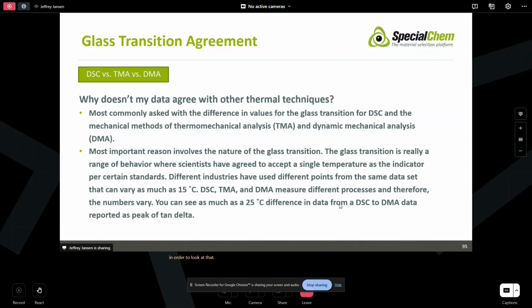I get a lot of questions about what's the best way to measure glass transition, because DSC measures it so importantly. Unfortunately, DSC is probably the poorest of the other techniques. You can get glass transition off of thermomechanical analysis as well as dynamic mechanical analysis. DMA is really the best way to look at it because it's directly measuring what glass transition is, the mobility of the molecule. In DSC, you're measuring heat flow, which is, we'll call it, an artifact or a side effect of that molecular freedom. So you're really not measuring what's going on directly during glass transition in that freedom of the molecule.